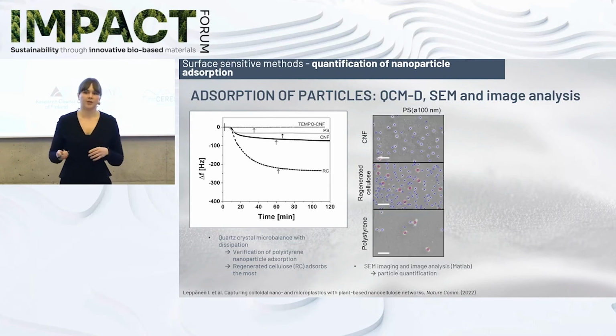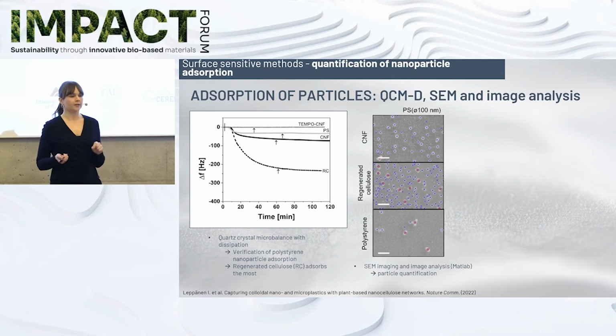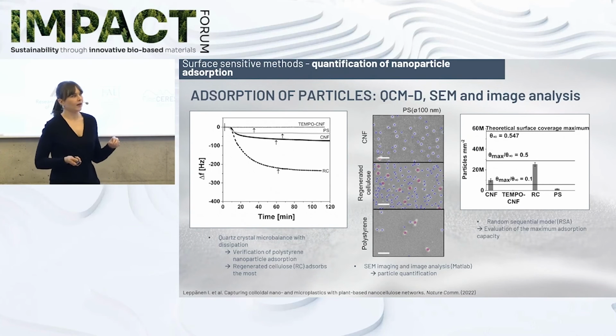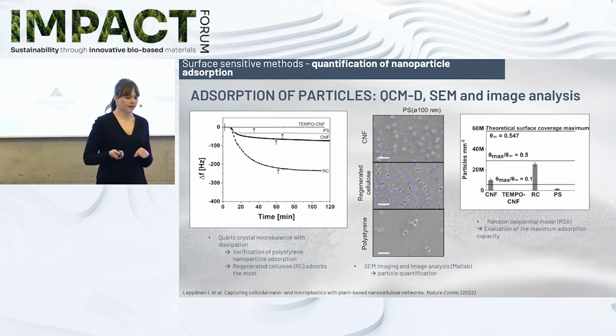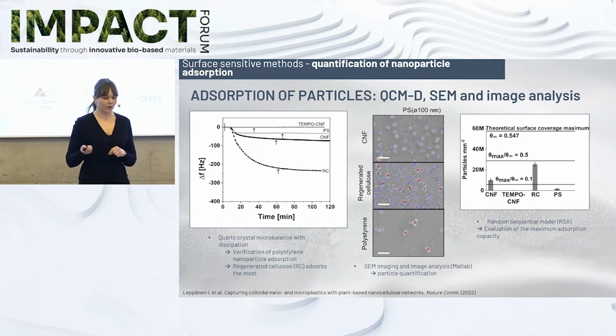Then we have applied this image analysis using MATLAB to detect the different nanoparticles to be able to identify and also quantify then the amount on these different surfaces. And then we have evaluated the efficiency of these materials and compared it to this theoretical surface coverage maximum, which is based on this RSA model. So the maximum coverage is 50% of the surface, and with the regenerated cellulose we're able to, in only a 1 hour test, reach already 50% coverage.